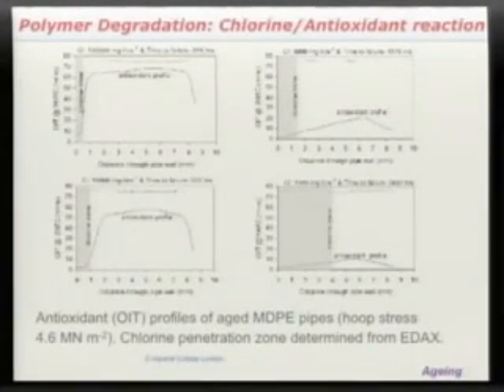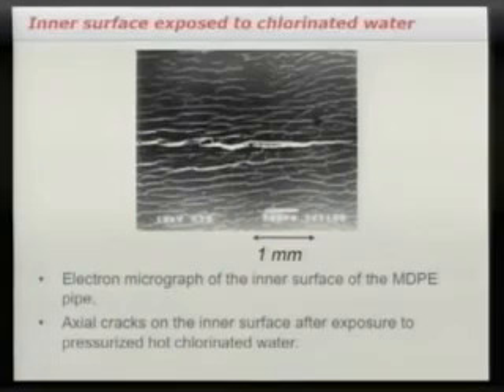My time is running out, so I'm going to go very quickly through this final point, which is we also looked at antioxidant loss from polymers. And the reason we were interested in that, this was a separate PhD project and a number of students were involved in this, is that the aging of polymers over a long period of time is determined by antioxidant loss. And aggressive agents like chlorine in water can diffuse into a polymer and start to consume the antioxidant. And we analyzed those processes.